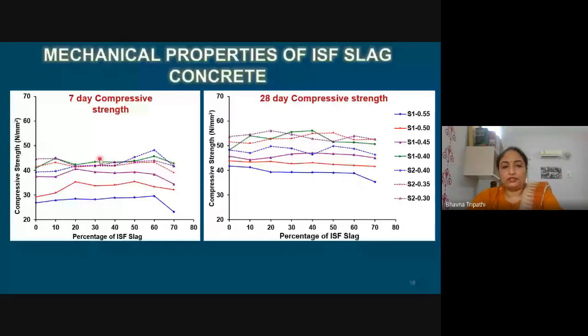In 7-day compressive strength, there was appreciable difference. For example, if we consider this mix, 0.50 water cement ratio, it has higher than control strength in all of the specimens. However, when we see the same mix in 28 days, the line is more straight. So the reason is that at 7 days, the compressive strength of ISF slag mixes was appreciably rapid. No, this would be a wrong reason, because ISF slag is doing nothing in hydration.